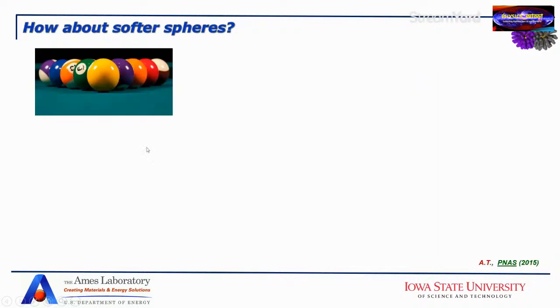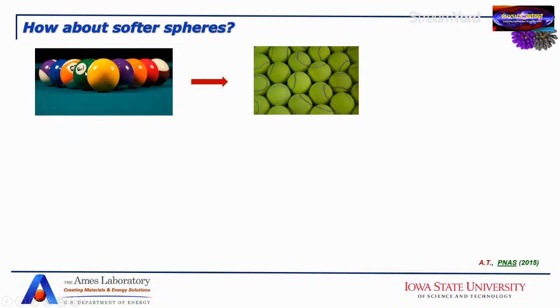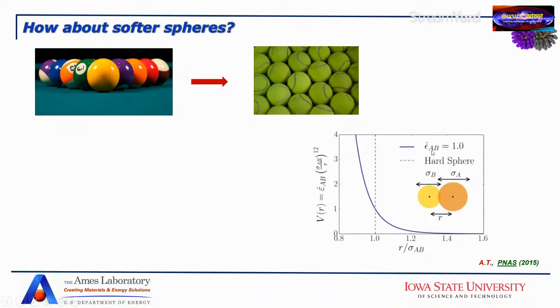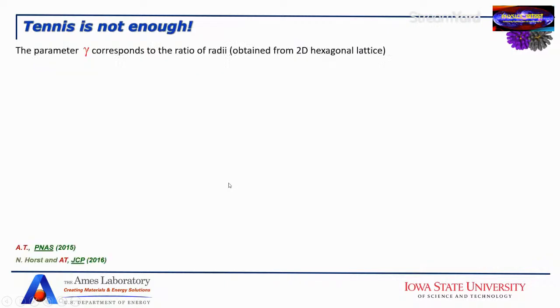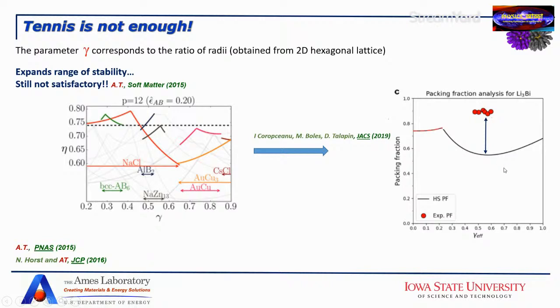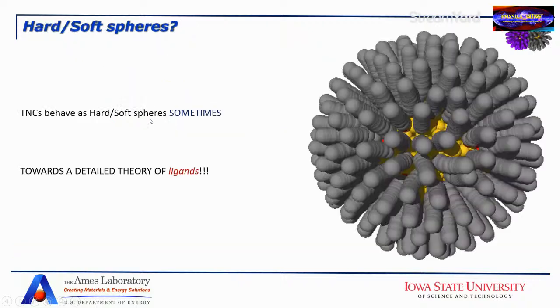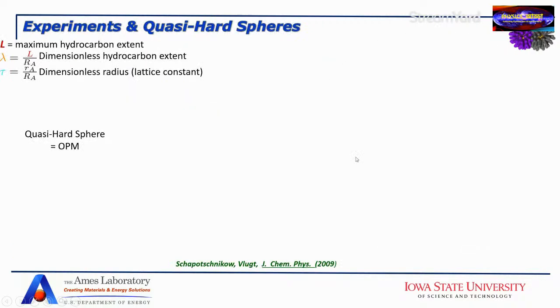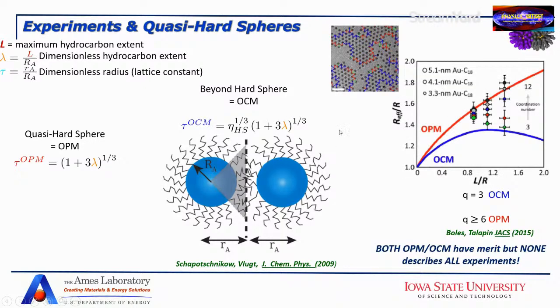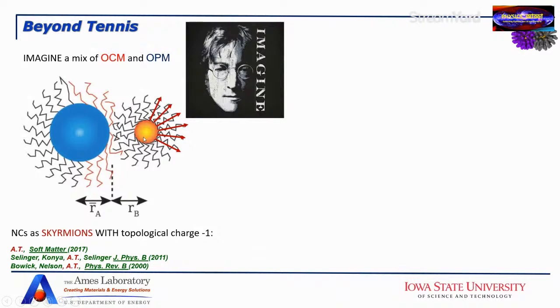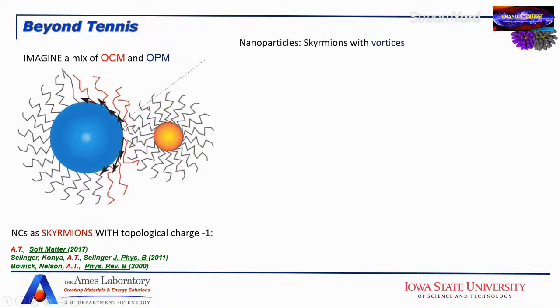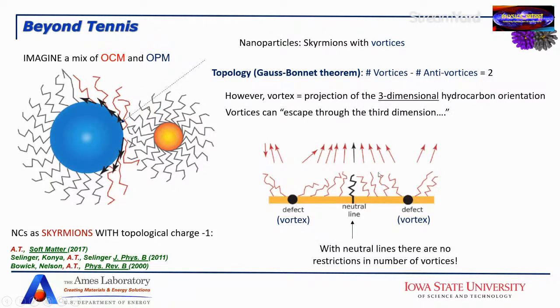Another step is, okay, instead of billiard balls, we make them into tennis balls, which are flexible. The idea is that maybe that will improve things. So instead of having a rigid potential, we let some particles overlap. And we've done this, and the answer is that it doesn't help that much. It's not possible to explain the experiments only with this. Okay, so what is next? Well, the next is to consider the ligands explicitly, and I'm not going to go into detail, but basically we developed a new theory where we have to consider the flexibility of the ligands and some topological considerations that have to do with topological defects and so on.